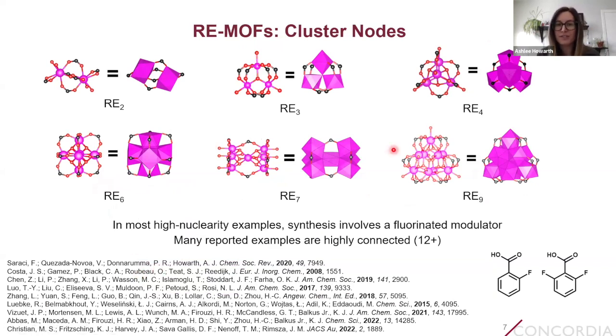So you can see the diversity in these clusters in terms of the nuclearity, the geometry, and the connectivity. And this type of diversity in building blocks is really exciting as a MOF chemist because we can make so many different structures. But it also poses a very significant synthetic challenge. Because all of these clusters are so easily accessible, it makes controlling the generation of one specific cluster in situ during the solvothermal synthesis of MOFs quite difficult to do.